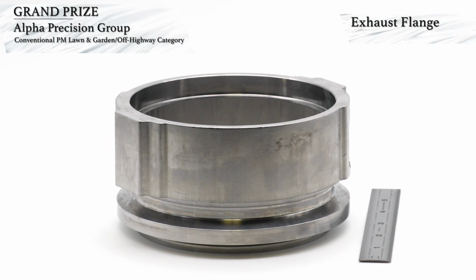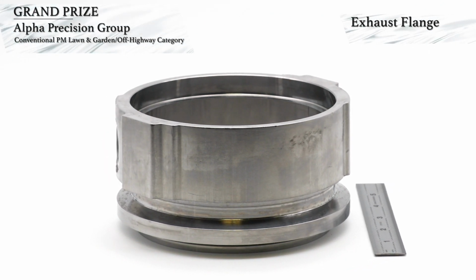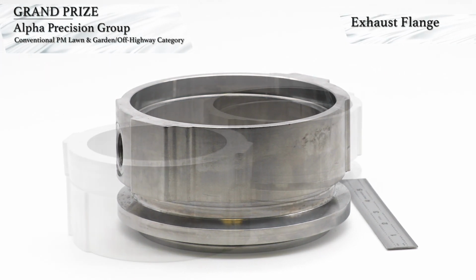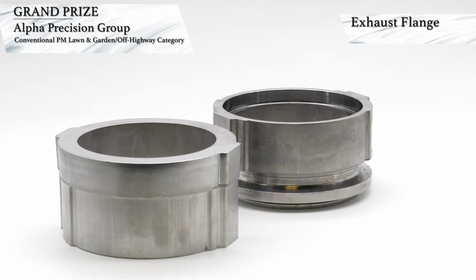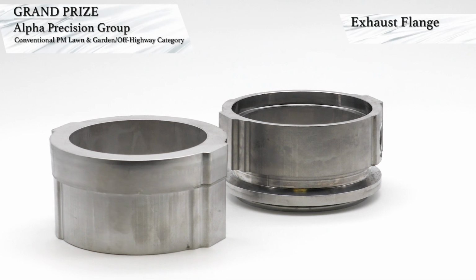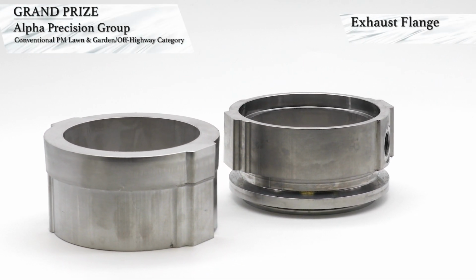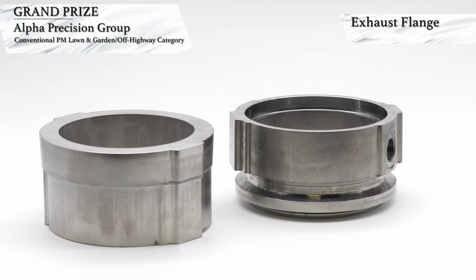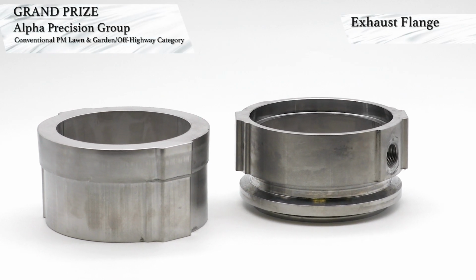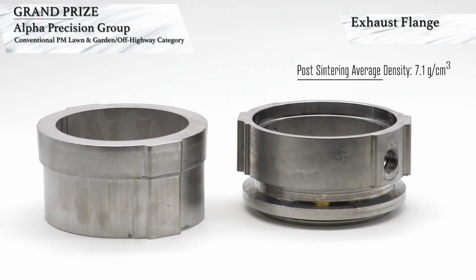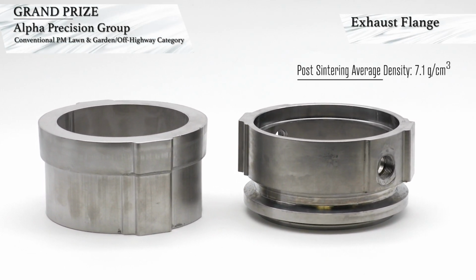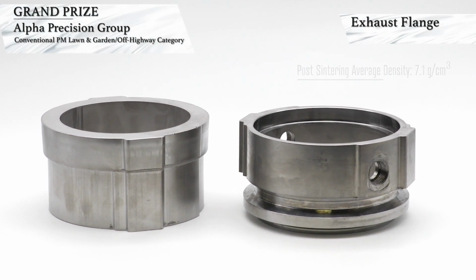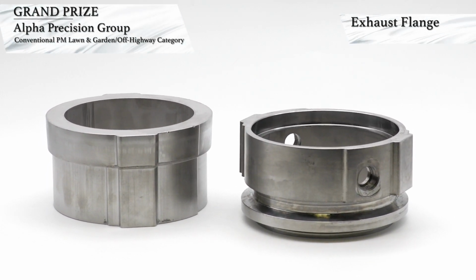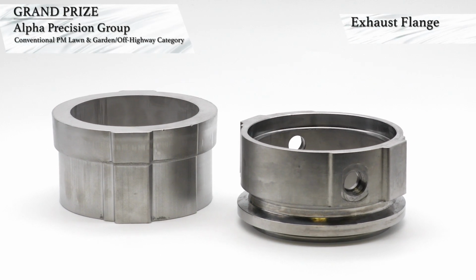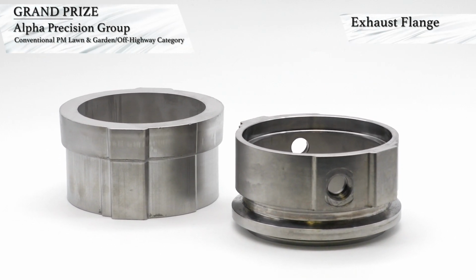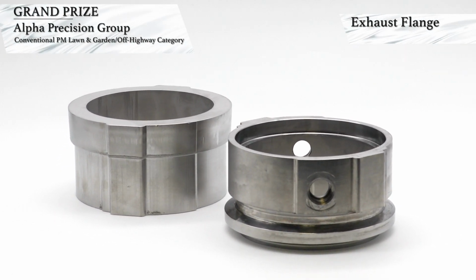Because of early galling problems, a die-wall lubrication system was used to supplement the admixed lubricant in the powder mix. The parts are compacted to an average 6.5 grams per cubic centimeter density, followed by delubrication and high-temperature sintering to reach 7.1 grams per cubic centimeter density. The high density is needed for weldability and to prevent leakage. The part combined what previously were 3 standalone components, a flange and 2 bosses.